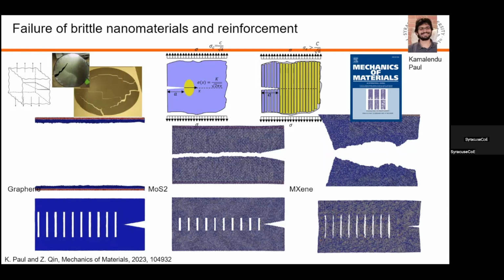But a way to enhance the toughness of this material to make it less affected by the pre-existing crack is to just borrow the concept from nature, which is to create some nano architectures. We simply create those bridge structures, turning a continuous 2D material into an isolated bridge structure. We think that if it's continuous, there will be high stress concentration, but if it becomes this bridge structure, the stress gets more distributed.